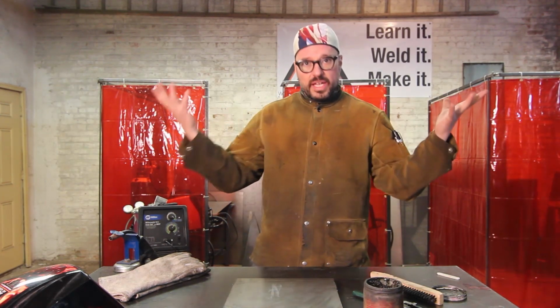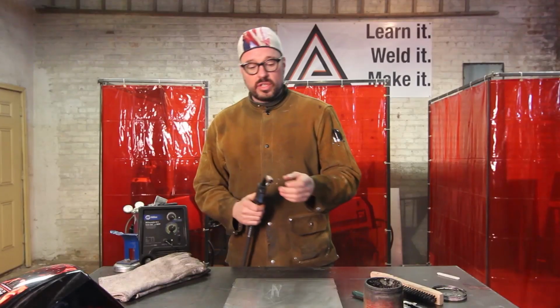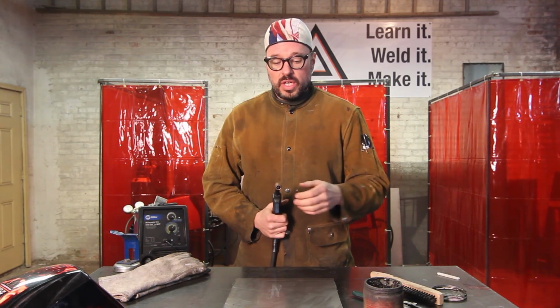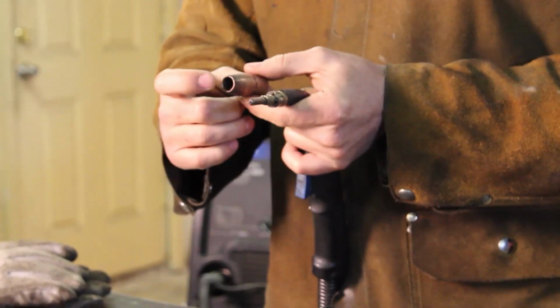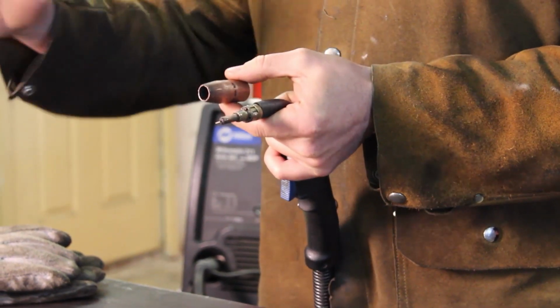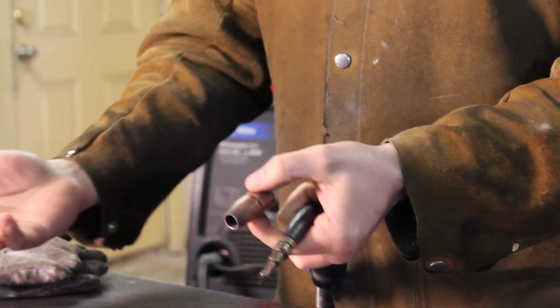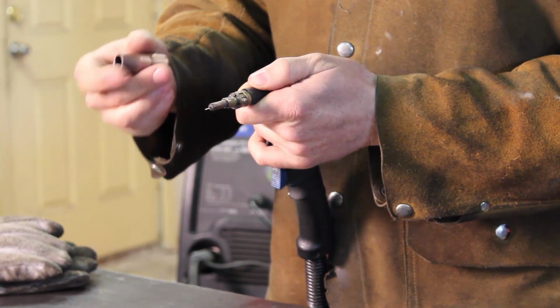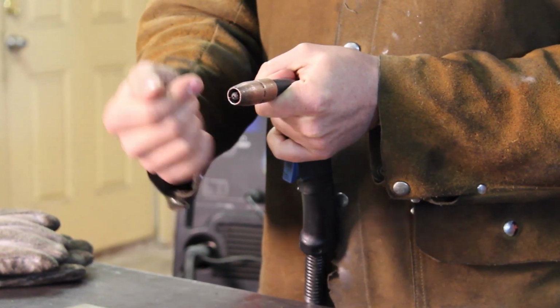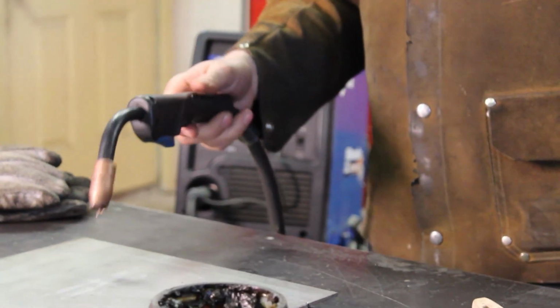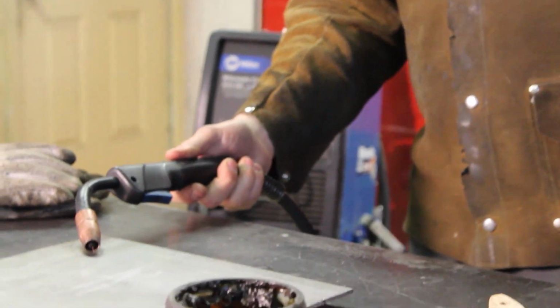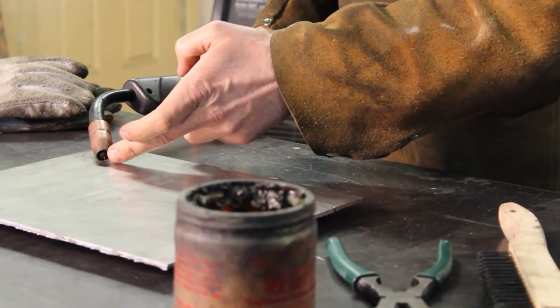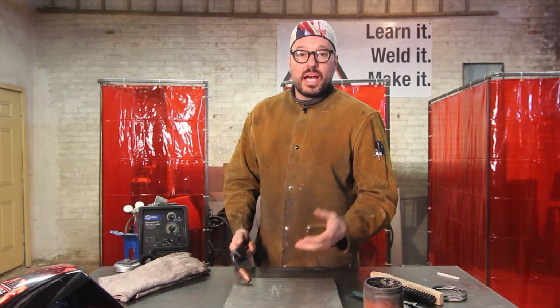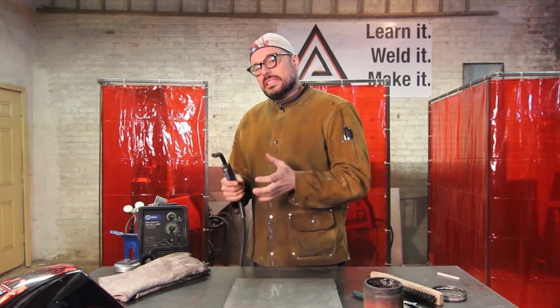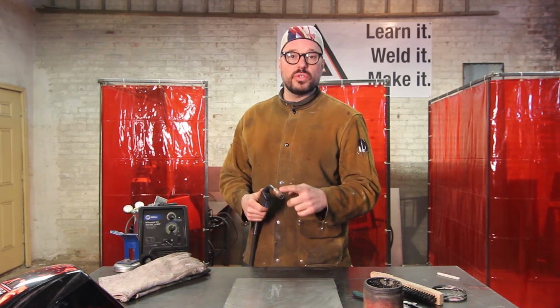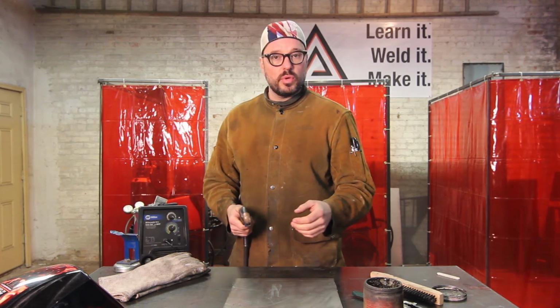So what happens? Well, spatter is flying out of the weld zone the entire time you are welding, and it can also go up inside of your nozzle. If you get buildup onto your nozzle and onto your contact tip, what happens is most of the time, most machines, your contact tip is live, okay? Your nozzle usually is insulated from the current going through it. But if you build up a conductive metal bridge in between your contact tip and your nozzle, you're going through your weld zone, you accidentally touch down, this is going to lead to what's called double arcing. You're gonna have an arc point at the edge of your nozzle and of course at your electrode wire. Higher voltages, once again, one out of 10 times, you're going to actually weld your nozzle to your piece. And that's not good because these are a little bit more expensive than contact tips.